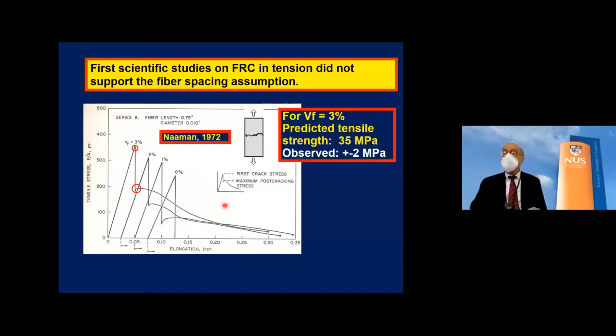So I ran quite a large number of direct tensile tests. At the time, even using an Instron universal testing machine, we would get load and displacement, but the displacement was between the platens, not like an LVDT taking exact strain. And you could then understand what the shape of these curves are. Typically what I observed, and 3% fiber is about as much as I could put from the fibers I had, was something like this: the load increases up to a certain point. There is a crack that happens. So I call this the cracking strength. And then it decreases, going back in a softening way. Along this part, the fibers pull out. I call this the maximum post-cracking strength. This is the cracking strength.